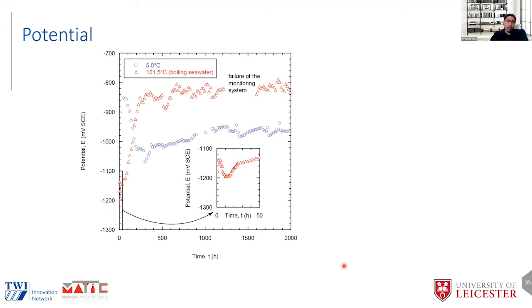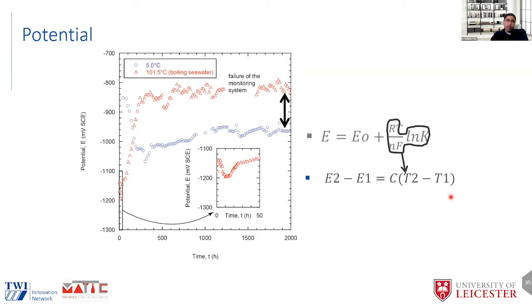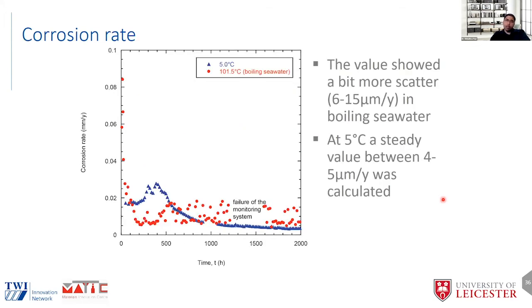When we looked at the other temperatures, 5 and 101 degrees Celsius, boiling seawater, again, we see that in both cases we are below the protective potential. There's a difference in the potentials at the two different temperatures, and we expect that from Nernst-type behavior. And we also saw the corrosion rate in both cases was still below 20 microns, in most cases maybe around 10 to 15 microns or so, at the temperatures of 5 and 101 degrees Celsius.